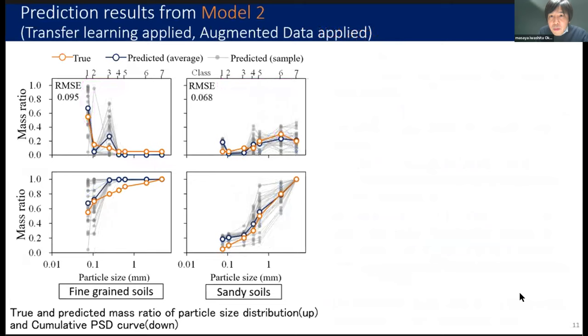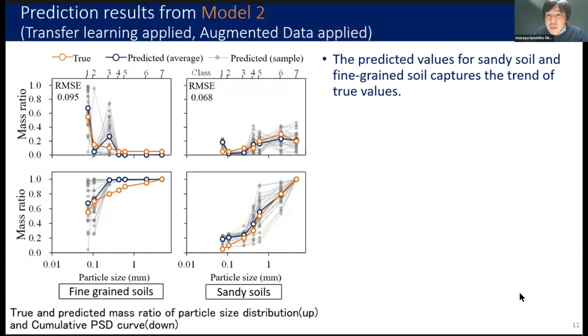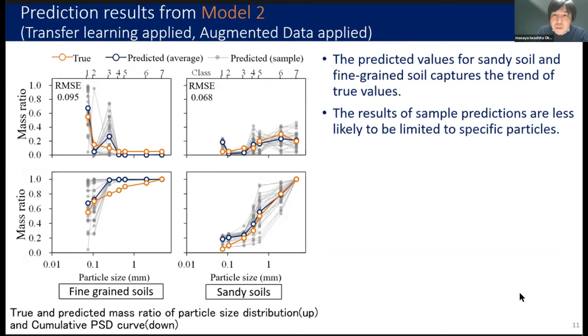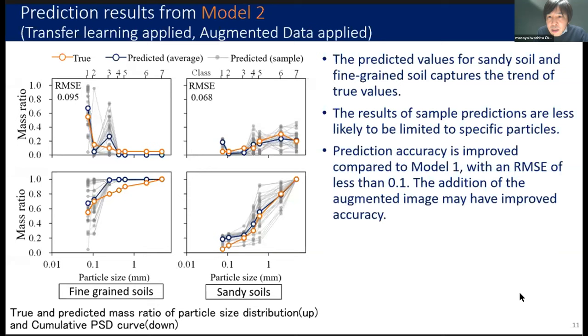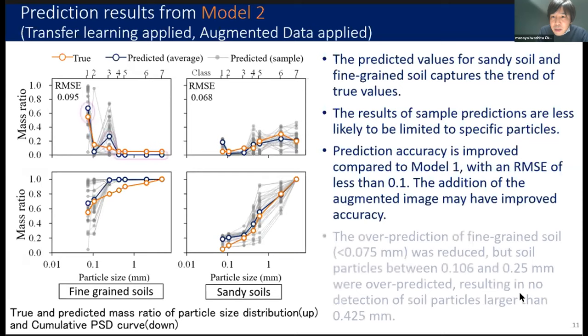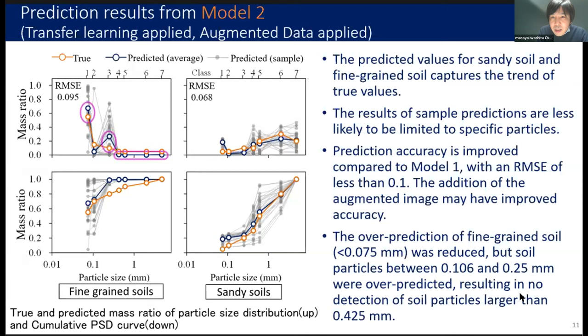Experimental results for model 2 are shown on the left. The predictions for sandy and fine-grained soils are consistent in the trend. The results of sample prediction are less likely to be limited to specific particle sizes. The accuracy is relatively good, with no particle size segment showing an error of more than 10%. This is thought to be the result of learning augmented data with split and joint images. The overprediction of fine-grained soil was reduced, but soil particles between 0.106 and 0.25 millimeter were overpredicted, resulting in no detection of soil particles larger than 0.425 millimeter.